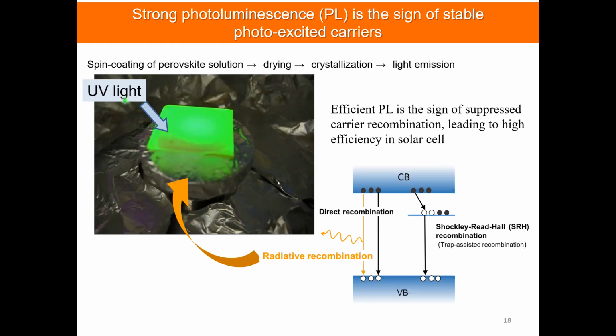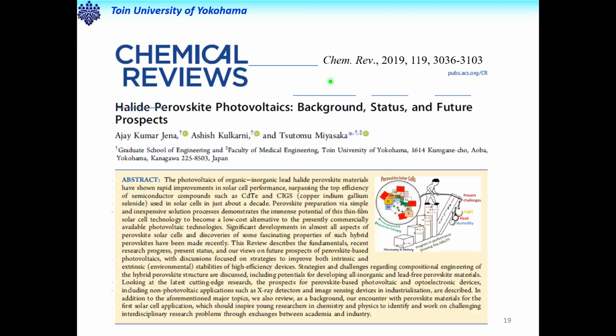So this was now exposed to UV light to excite the perovskite, and it was coated on an alumina insulator. If we replace this substrate with, say, a conductive electrode, all this energy is converted to photocurrent. So this very intense emission indicates how stable the photoexcited carriers are in the perovskite. This kind of outline we summarized in our recent paper in Chemical Reviews.